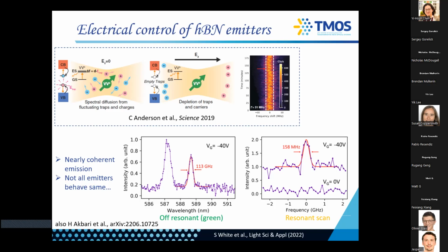So this is a way to engineer your single photon sources in hBN. If you make them into these devices, you can get Fourier transform limited lines and hopefully then generate indistinguishable photons. We haven't done the indistinguishability yet, but this is now stable and reproducible. I also would like to mention a beautiful work from Akbari here on arXiv. They did the same thing with a device, and they also saw that when you increase the bias, the lines become much, much narrower. So it's a very cool effect.